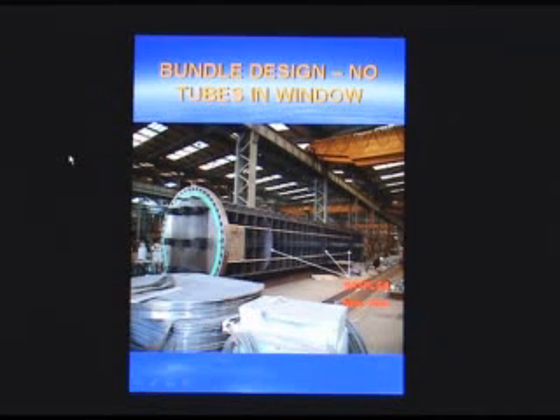span of the tube to minimize, again, cross flow vibration, which is caused by vortex shedding of the flow as it goes across the tube. The longer the unsupported span, I don't know if you've ever encountered a flagpole in a wind. It's very interesting to see. You'll occasionally see the flagpole will start to vibrate, and it'll have different node points depending on how it's vibrating. So the same thing can happen within a shell and tube exchanger, and what will happen there is that the tubes will actually vibrate to the point where they can collide with one another. That will cause erosion points where the tubes are colliding, and that will lead to tube failure.